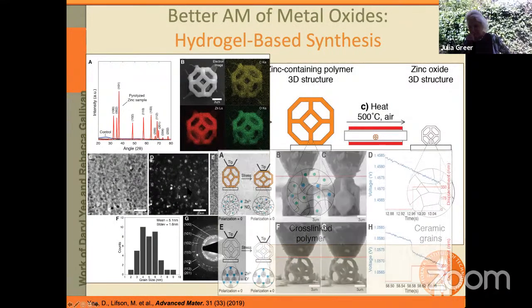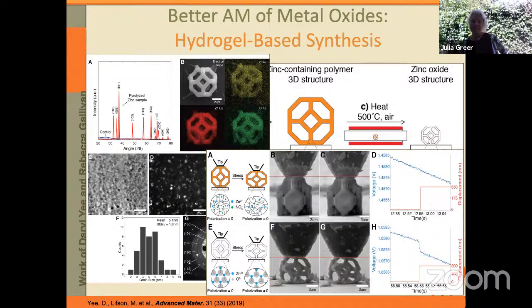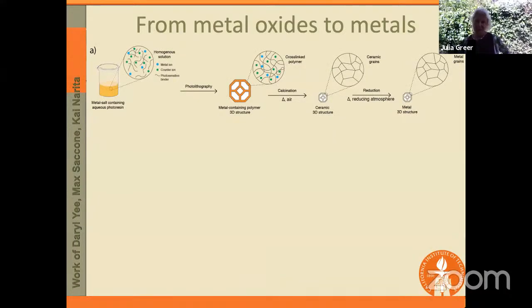And what's really interesting is that zinc oxide has a functionality of being piezoelectric. So you can see that, for example, here's one of those zinc oxide architectures. And when we apply mechanical load to it, it displaces. So what you see here, plot on the bottom right, it's not perturbed. Then we apply 200 nanometers of displacement, and you can see that there's a simultaneous voltage response, so that we still experience piezoelectricity even though it's nanocrystalline.